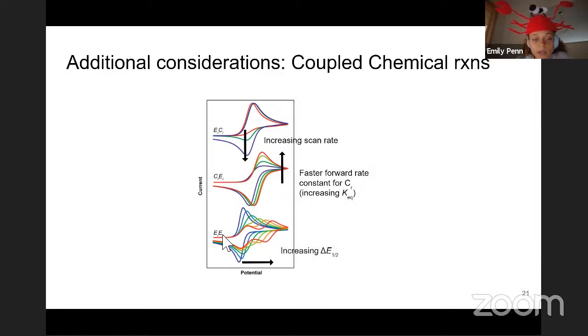And then lastly, we have an example of two consecutive electron transfers. In this case, the difference is we're changing the separation between the peaks. In the red line, this is the case where the two electron transfer reactions have potentials that are pretty far away. But as we go to the blue curve, this is still a plot for two consecutive electron transfers, but the potential of the second transfer is negative to the potential of the first transfer. So it actually merges together to form one peak.